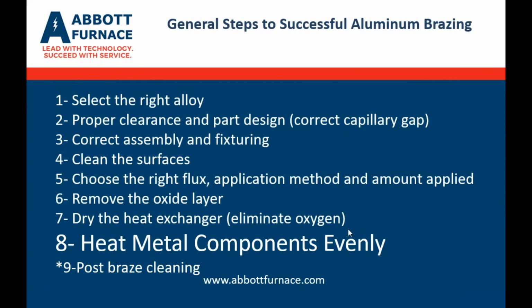Heat the metal components up evenly. When it comes to temperature, we want to be plus or minus 5 degrees or 3 degrees C at brazing temperature. And then any kind of post-braze cleaning that's required.